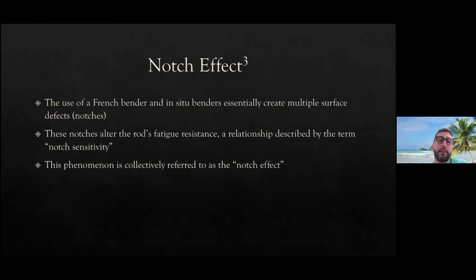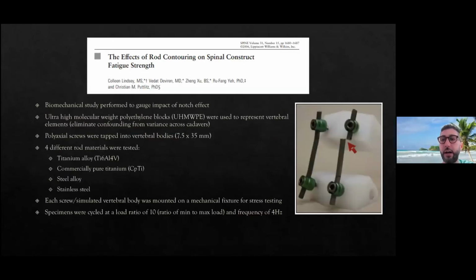And the problem is that these notches that we place in the rods actually alter the rod's fatigue resistance. And that's described by the term notch sensitivity, and this overall phenomenon of fatigue resistance being decreased via notches is referred to as notch effect. This is not just like a theoretical construct. It's been well described in the literature.